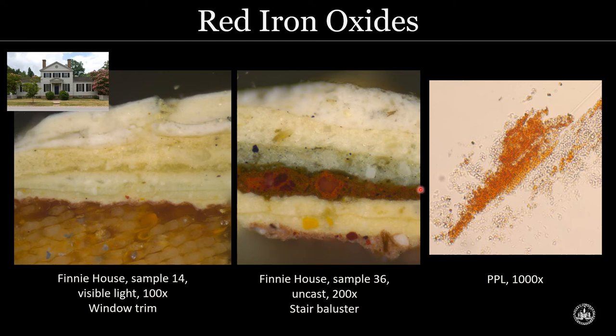And then later on, we have another paint. This was actually a deep chocolate brown color, although it appears red in the cross section. This also was made with iron oxide pigments. And here you can see this really great large particle of silicate surrounded by finer bright red grains of hematite. And on the right, you can see a dispersion of the red iron oxide particles collected from the primer for polarizing light microscopy. And it was also mixed with a lot of lead white and other pigments.